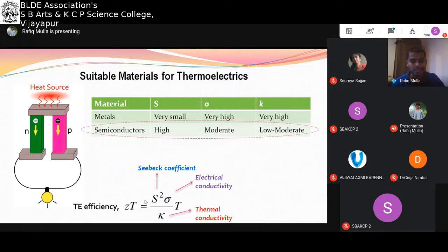Another question from Wadiraj: is there any alternative way instead of placing thermoelectric elements in series within generator modules to get voltage output levels in the range required by digital electronic devices? So when we put in series, that depends on how much potential we need and how much temperature gradient we are applying to the device. If you use only one junction and apply more temperature gradient, then you can also get sufficient voltage from a single junction. In such cases, you need to have very long conductors, which is not suitable for practical applications. So that's why people try to make devices as small as possible. Because of that, people prefer to use multiple junctions, so that a thin device with a small temperature gradient can create sufficient voltage to power small electronic devices.